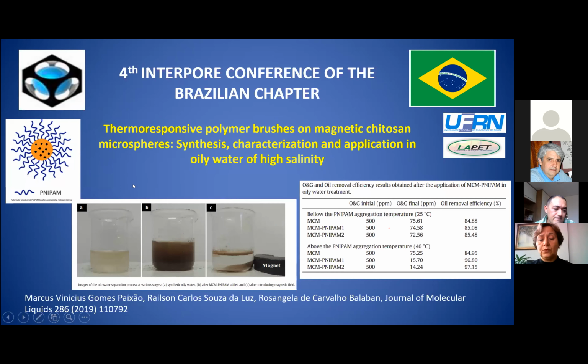In this second work, we evaluated the effect of thermoresponsive polymer brushes on magnetic chitosan microspheres. So now we worked with chitosan, that's a polysaccharide obtained from chitin, that's an animal polysaccharide, that can be found in the shells of crustaceans. So we used this polysaccharide, chitosan, to obtain microspheres.